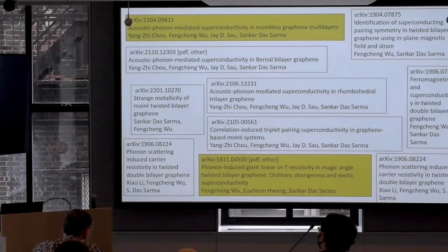The situation is this: it's a very complicated material. There are so many phonon modes. And what I learned from my material science friends is that it is also very disordered, very inhomogeneous. So you may have phonons you don't even know about, local vibrations and so on. So it's not easy to do. But if you look at the raw numbers, first, this statement that it is linear down to very low temperature is very misleading in two ways. One is that it is linear down to very low temperature in very high magnetic field. Now, I'm not saying a magnetic field will change the phonon structure very much, but that's not the system we are talking about.